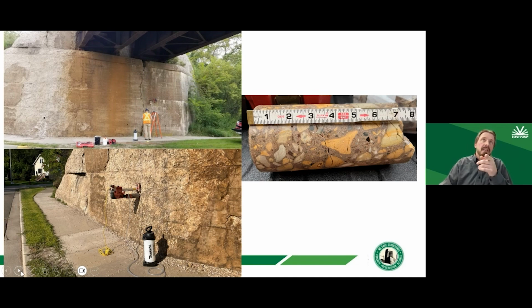For the abutment on this pier, we were able to take a lot of the bad concrete off and do an encasement, add dowel-in reinforcing, put a mat up, and shotcrete it back. You can see right there is a sidewalk, and the road is right next to it. So we didn't have a lot of room to provide an overbuild, right? But there was enough concrete there that we could remove the bad stuff and just do a conventional encasement. There was no carbon fiber on the abutment.